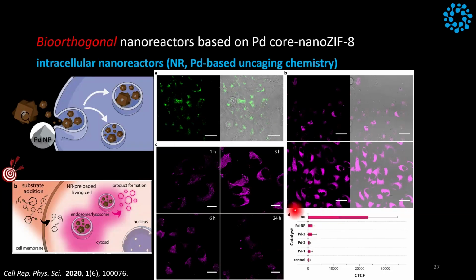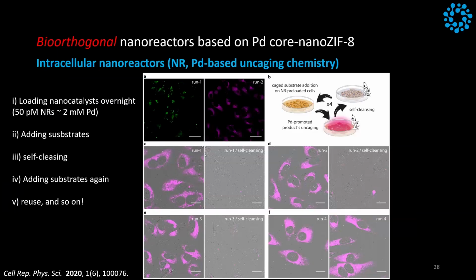We compared it with palladium nanoparticles, and it doesn't work. You see, this is the nanoreactor, this is the palladium nanoparticle, and these are three widely used homogeneous palladium catalysts. Okay, just so that you see, we put the same amount of palladium and see how much of this we could get. And something very cool is that with the same cells, we could do one run to express one fluorescent product, clean it, and make a second one.